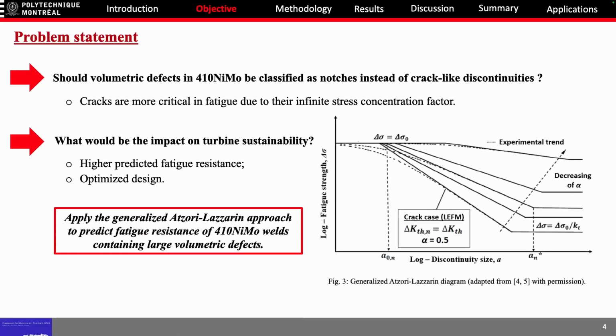The general objective of this project is to apply the generalized Atzori-Lazzarin approach to predict the fatigue resistance of 410 nickel molybdenum containing large volumetric defects. Basically, this is a diagram which predicts the fatigue strength as a function of the discontinuity size, but for different singularity exponents. For a crack, the singularity exponent is 0.5, but when we consider notches, the singularity exponent is decreasing.